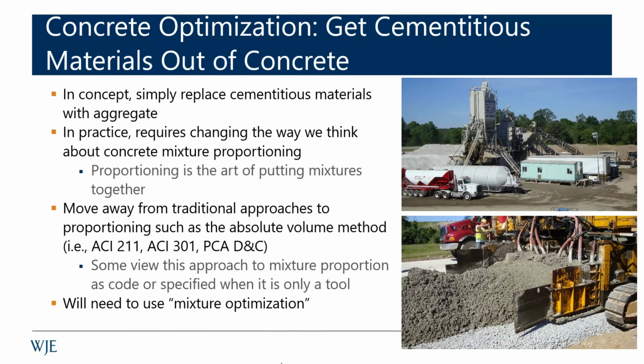And I want to say this started before even the thought of using it to decrease embodied carbon on concrete. We're looking here really to try to get a mix with great workability. A lot of work was done for the slip form paving industry, but it's now been extended for pumping concrete. And the idea, as I said, very simply is to pack more aggregates into our concrete mixtures of select sizes so that we need less paste. We need less paste, we can cut back on our cement, yet get as good or better workability.